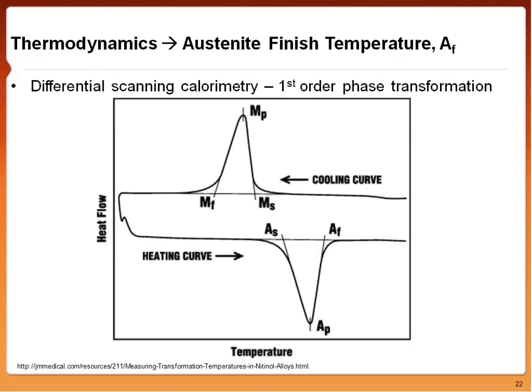So what this is exhibiting here is called a differential scanning calorimetry curve. For industry, this is what we mainly use when we examine bulk ingot or raw material. What it basically says is, as we change the temperature of a sample, we can monitor the heat flow in and out of that sample. This gives you the most accurate transformation temperature of your material, but it doesn't say much about how your device will function at its so-called finish temperature. It gives you the finish temperature of a bulk ingot, but it doesn't really tell you that well how your device is performing at its Af temperature.